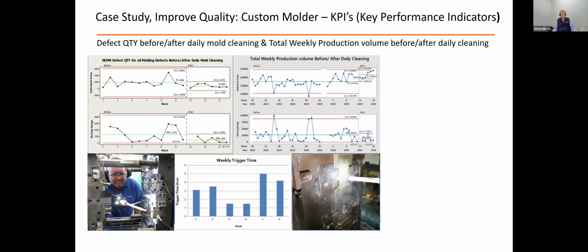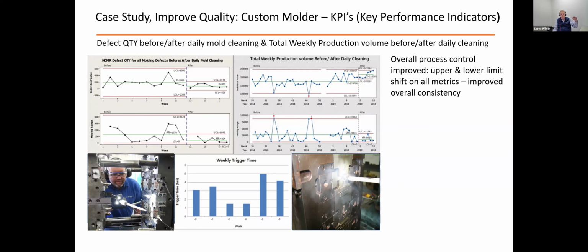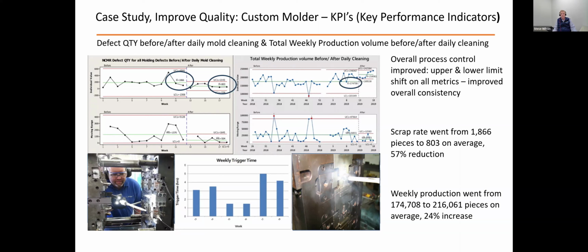This is defect quantity before and after they started cleaning with dry ice, total weekly production before and after cleaning with dry ice. Look at those screens, look at those bars. Note the process control improved across the board. The upper and lower control limits shifted on every one of the metrics, and the overall consistency got better. The scrap rate went from 1,866 to 803. That's a 57% reduction in scrap. The weekly production went from 174,000 to 216,000, a 24% increase.